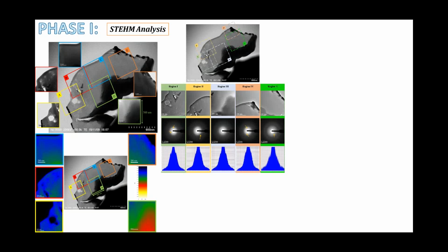And also, I went on to look at the structure of my sample, so I used the electron diffraction pattern. From this pattern, you can tell if you have a crystalline structure, an amorphous structure, or something in between. Again, I divided my sample into 5 regions. From each region, you can see that there is no evidence of crystallinity, but from the red arrow, or yellow arrow, I should say, you can see short-range ordering. But generally speaking, these samples turned out to be an amorphous structure, because you can see it from the diffraction pattern in the middle of the photo.